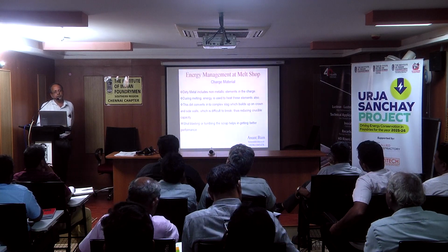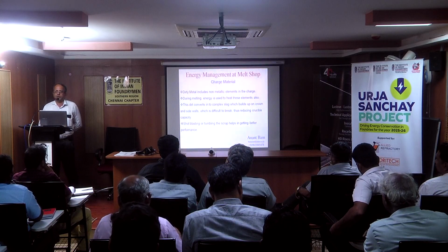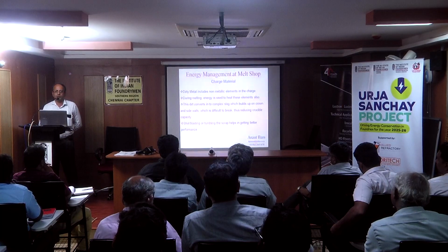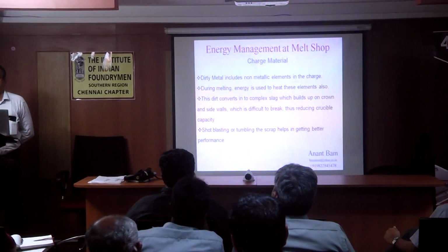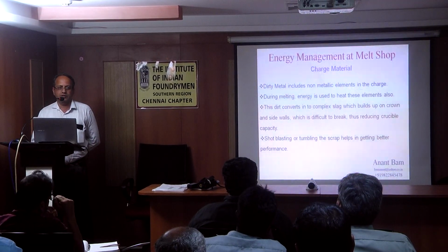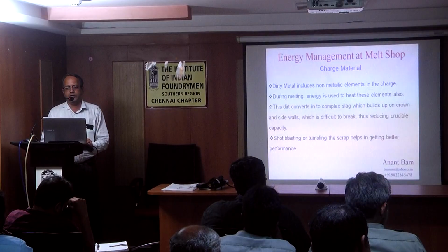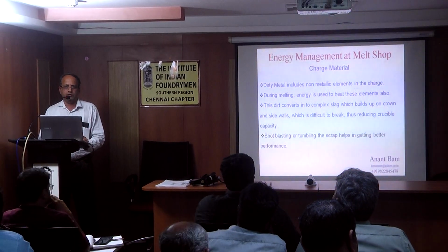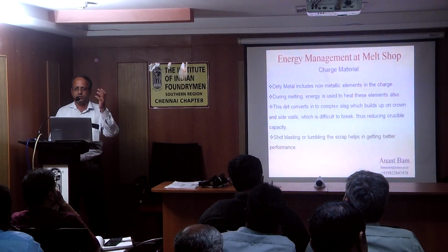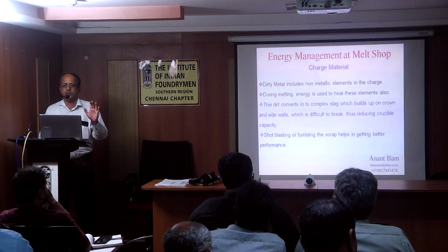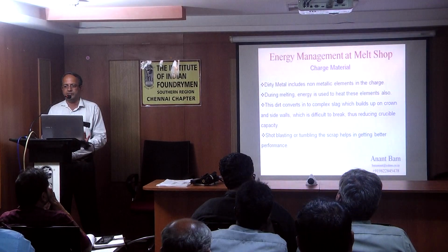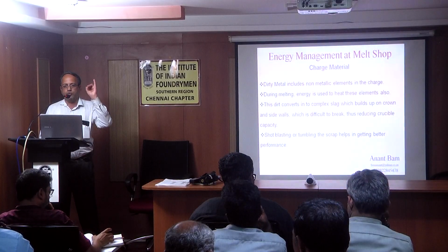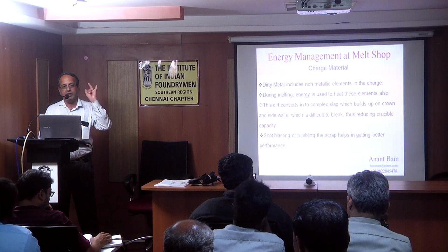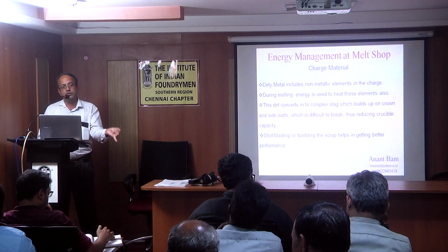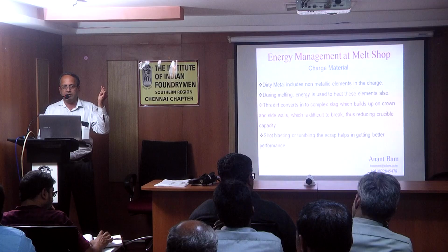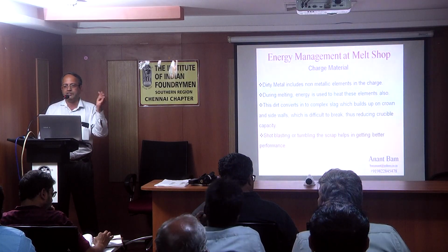Charge material. Again, it's a commercial question. I would say techno-commercial. Clean charge material gives you the best results. Because unclean charge material, dirt, dust, oxide, whatever it may be, grease, sand stuck to the runner riser, it's something else which you don't want in liquid metal. It's occupying the volume of the furnace. It's taking energy from the electricity which you are supplying to take to that temperature, because the specific heat capacity of sand is larger than the specific heat capacity of iron.